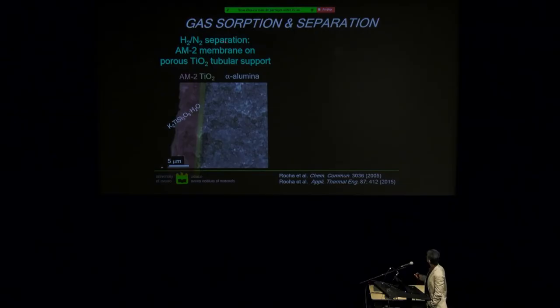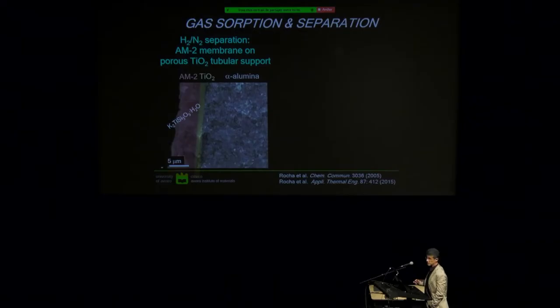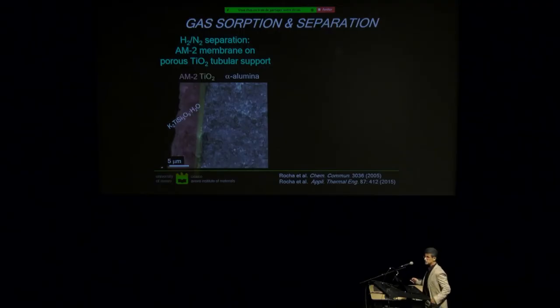And so, for example, gas adsorption and separation. Of course, when you make something like a zeolite, you want to explore properties people normally study with zeolites. And gas adsorption and separation is, of course, an important field. So we were able to make membranes of a particular microporous material here, glued to a mesoporous alumina. And this is a tubular support. And with this, we could separate hydrogen from nitrogen at 60 C, even in the presence of water, by a factor of about 40.